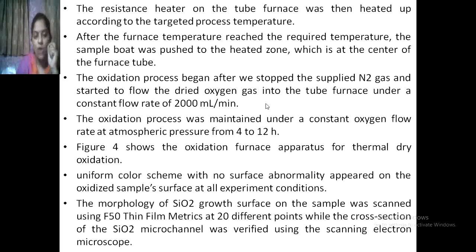Then the oxidation process began after we stopped the supplied N2 gas and started to flow the dried oxygen gas into the tube furnace under a constant flow rate of 2000 ml per minute.